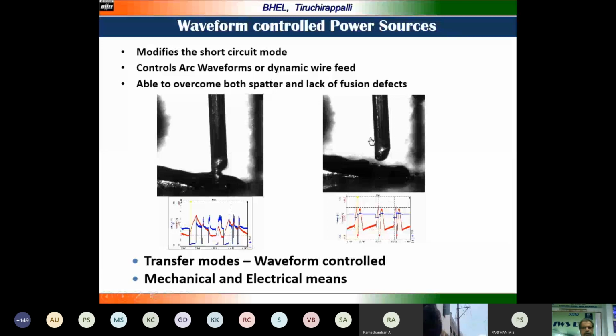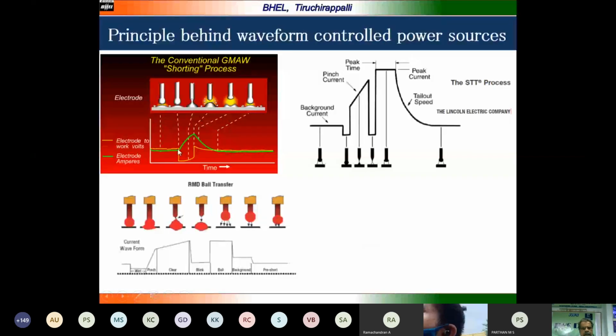Here you can see again the waveform is connected. You can see the current here, how high it is. Here the current is not going continuously high, it is going like pulse current, and the peak current is going for a shorter while when it is getting deposited. It is for the STT process, which is a trademark of Lincoln Electric. It is RMD by Miller, and both are the same technologies, only the waveform is different. But one thing is they are very low heat input deposition processes for thin sheet application and root pass welding with higher speeds. That is the advantage of these waveform control power source processes.